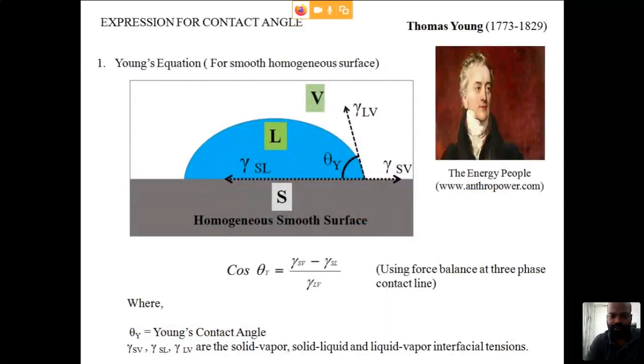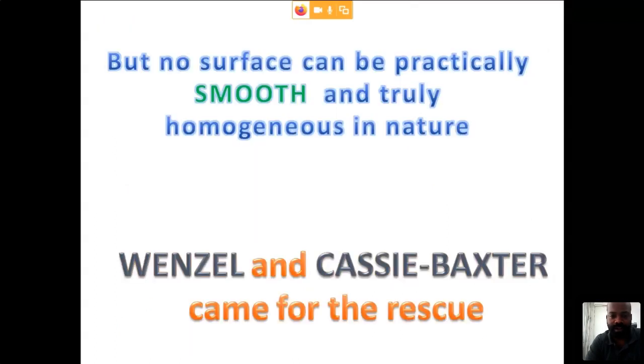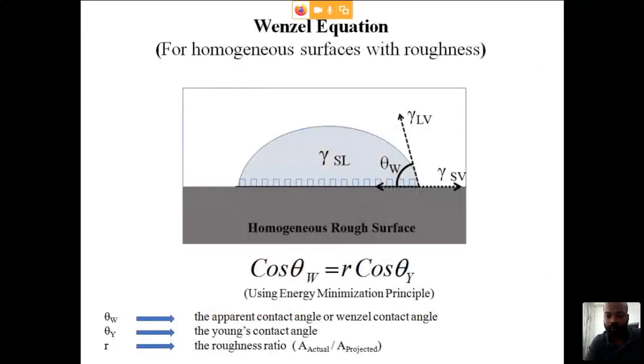Now this is Young's equation, which gives the contact angle on an ideal, homogeneously smooth surface. And we are moving towards the Wenzel and Cassie-Baxter states, since no surface can be homogeneously smooth. Here we are assuming the practical case of a rough surface. This equation involves the roughness of the surface, and it is very important because here we assume a homogeneous surface, but with some roughness.